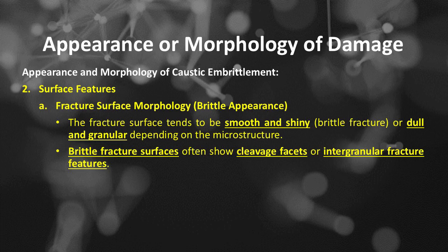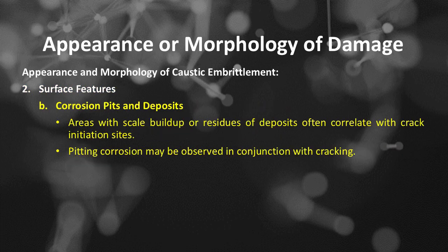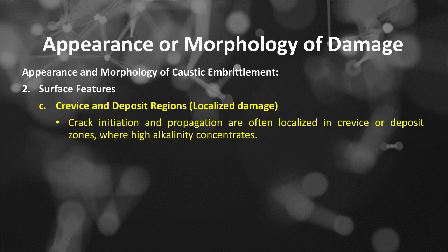Brittle fracture surfaces often show cleavage facets or intergranular fracture features. Surface features, number B, corrosion pits and deposits. Areas with scale buildup or residues of deposits often correlate with crack initiation sites. Pitting corrosion may be observed in conjunction with cracking. Surface features, number C, crevice and deposit regions or localized damage. Crack initiation and propagation are often localized in crevice or deposit zones, where high alkalinity concentrates.